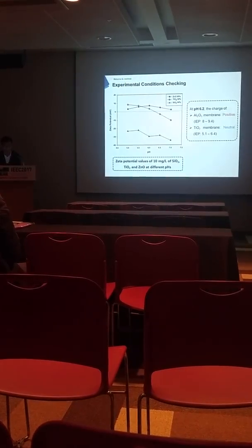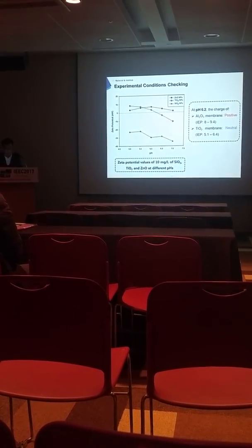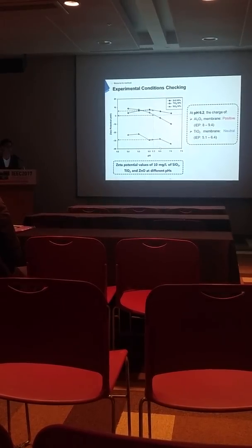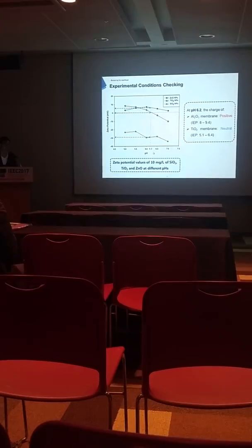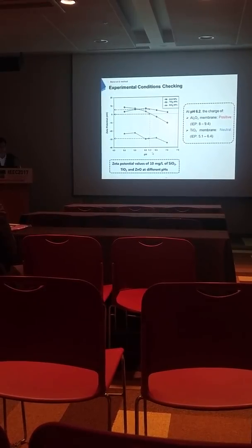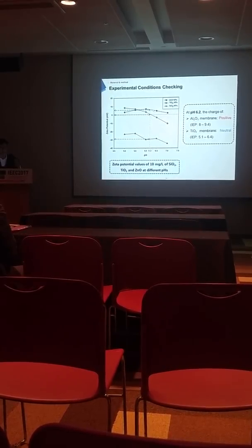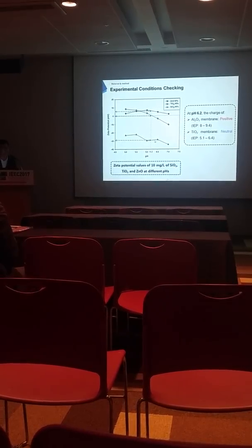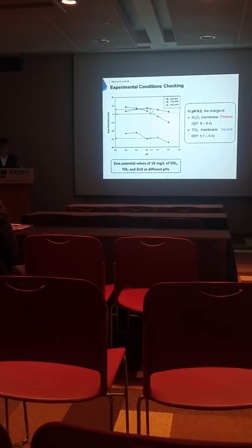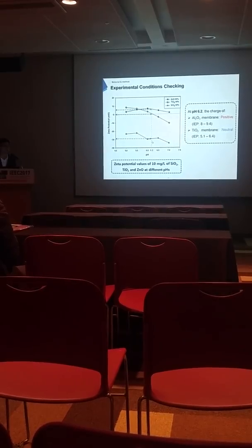I move to the third part, the results and discussion. The pH that we use in this study is pH 6.2. The reason that we use this pH is because at this pH we have zinc oxide, titanium oxide, and silicon oxide nanoparticles. They have positive charge, neutral charge, and negative charge respectively.